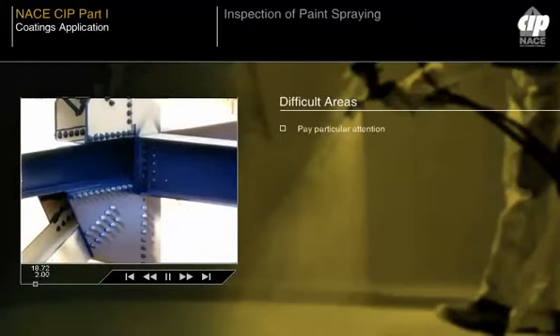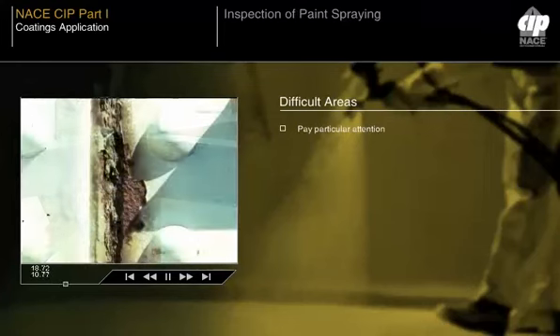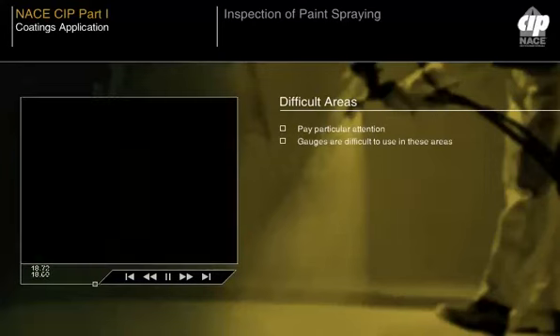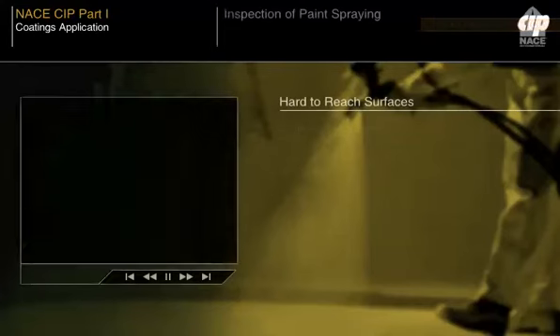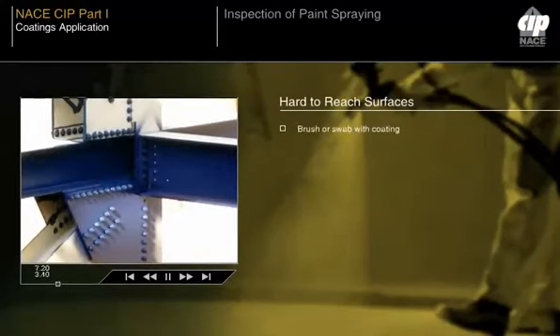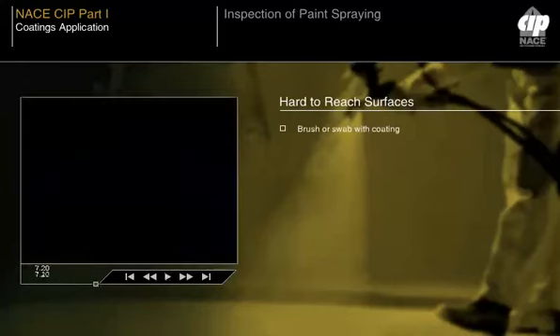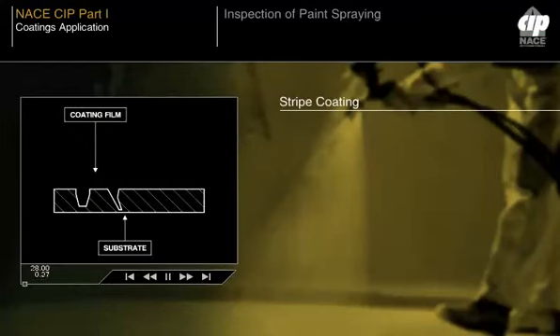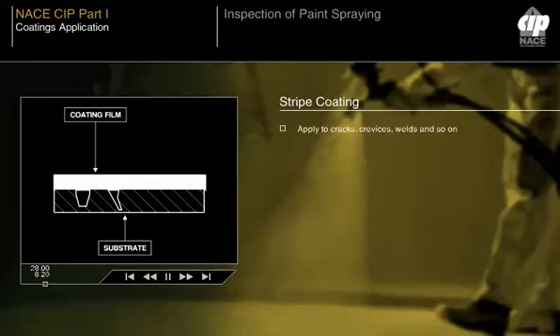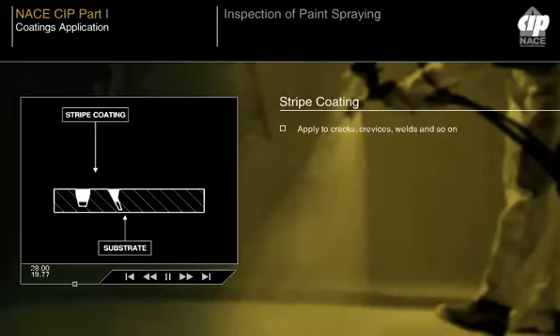The inspector should pay particular attention to the spraying of crevices, corners, welds, bolts, rivets and sharp edges, since these areas are generally slighted in spray application of coatings and cannot easily be checked with a film thickness gauge. Surfaces hard to reach by spray application should be brushed or swabbed with coating. Some coatings have a tendency to bridge across instead of fill cracks and crevices in the substrate. If called for in or allowed by the specification, a stripe coat should be applied to cracks, crevices, welds, etc. Stripe coating consists of brushing the coating into cracks, crevices and corners, etc. in order to work the coating into the narrow openings.